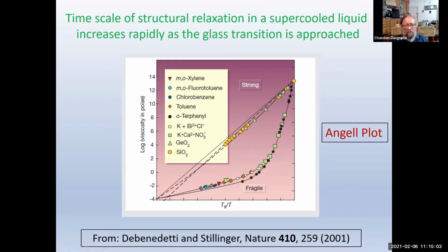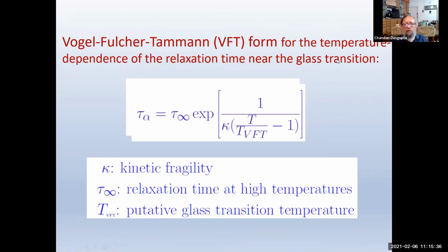And we'll be interested in this kind of dynamics and try to find out, for example, if instead of looking at the standard systems, we now look at active systems, whether again one has a similar behavior or something else. So to analyze that, one has to have some description of these lines that are drawn through these data points. This line, as I said, is simple Arrhenius dependence, but for this line with a lot of curvature for fragile systems, one has something known as the Vogel-Fulcher-Tammann form, which produces a pretty good description of how the relaxation time or the viscosity grows as one reduces the temperature.